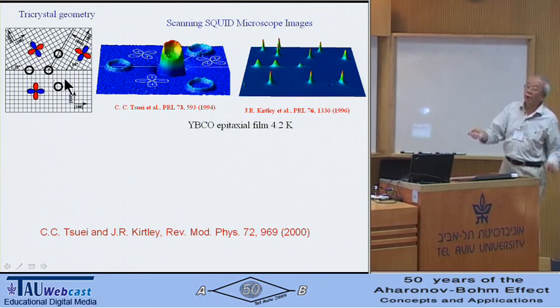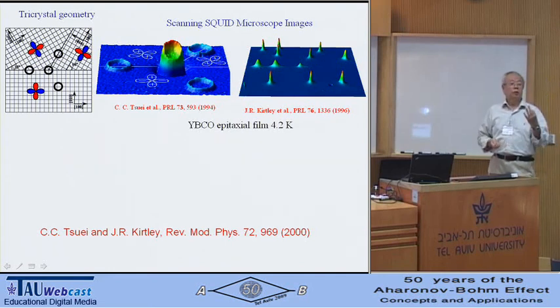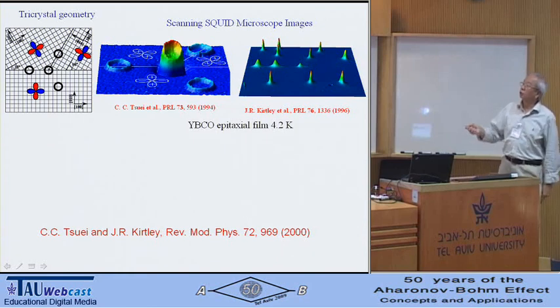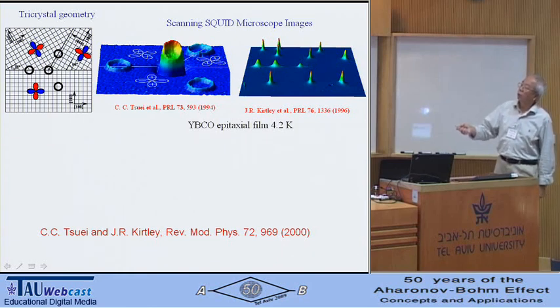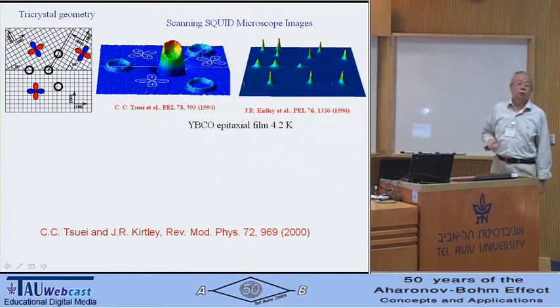and if you pattern a high TC film ring on it, then at the tricrystal point, it has 3 junctions and the sign changes once. Therefore, if it's a D wave, like I showed here, it should show a half-flux quantum at the center ring, but not the other ring. The other ring is just the control of my experiment.